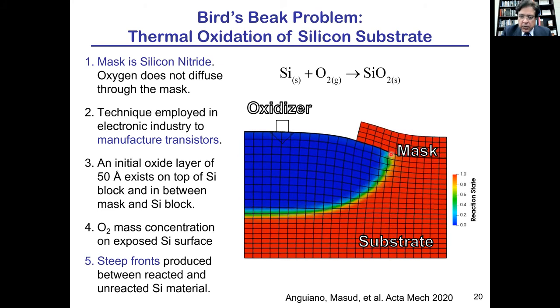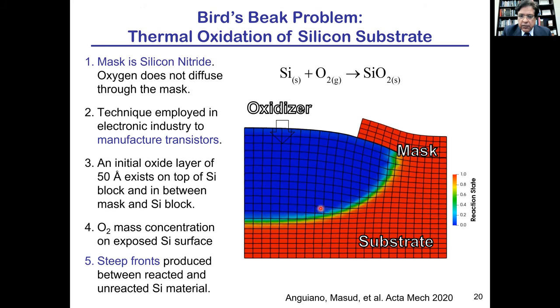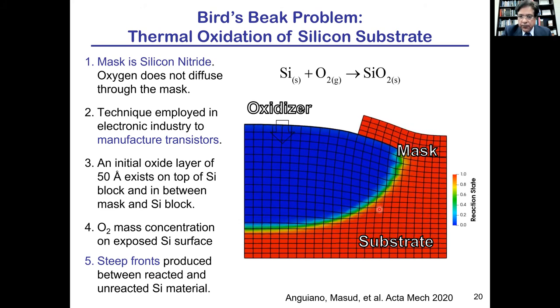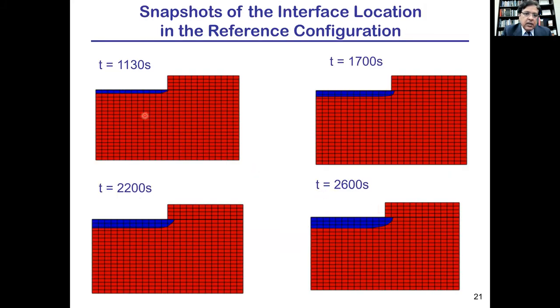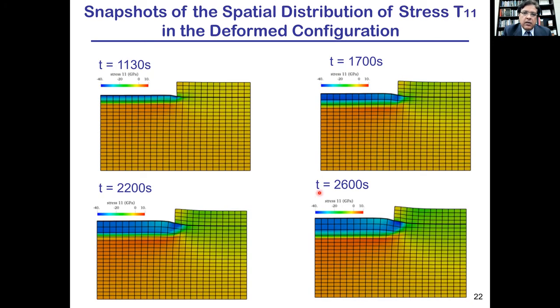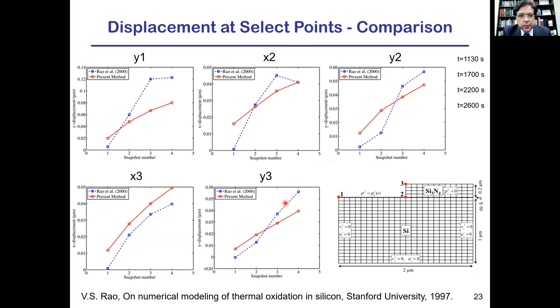So we're going to look at this steep front that is moving across the domain. Here are snapshots of this front in the reference configuration, and we see that we can capture it with a very smooth profile. Here are snapshots of the stress sigma 11 at different points in time along the evolution of the problem.